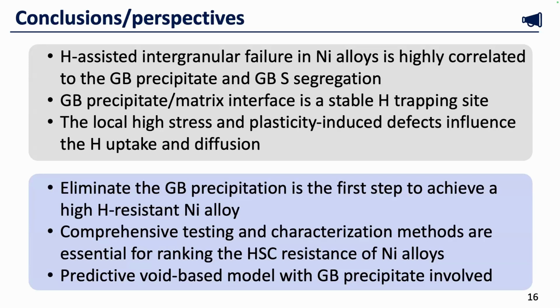Comprehensive testing and characterization methods are essential for ranking the hydrogen stress cracking resistance of nickel alloys, which means deciding which technique we should use to select the proper material. And the predictive void-based model with grain boundary precipitates is highly recommended.